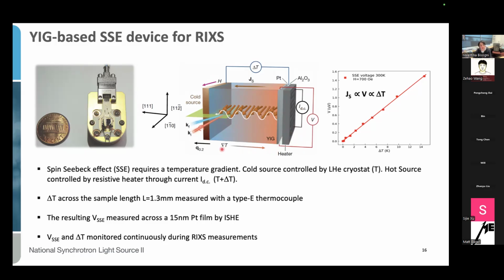So in this way, the thermal gradient goes from left to right, where the cold source sets our temperature T, that is the base temperature of the cryostat, and the heater sets our high temperature, that is T plus delta T. And in order to know our delta T, we implemented a thermocouple wire across the edges of our crystal to get access to the thermal gradient realized in our device.